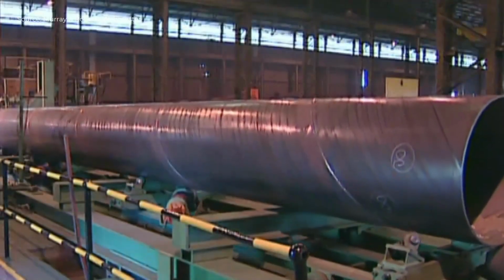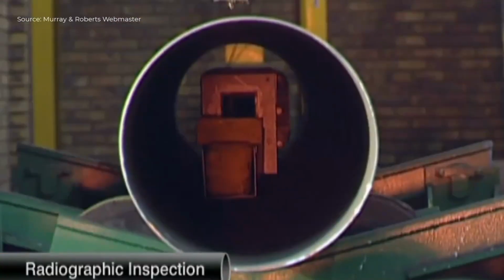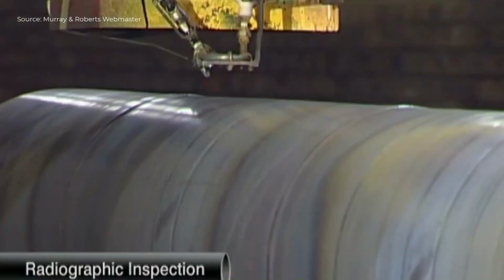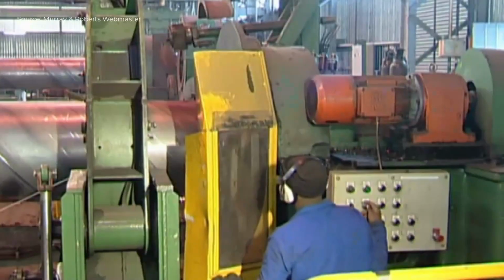Flux temperature, humidity, and flow rate are tightly controlled. All weld seams undergo continuous ultrasonic testing for defect detection. Pipes are cut into single lengths by air plasma cutters. Finally, pipe ends are machined to ensure precise bevel angle, blunt edge, and perpendicularity.